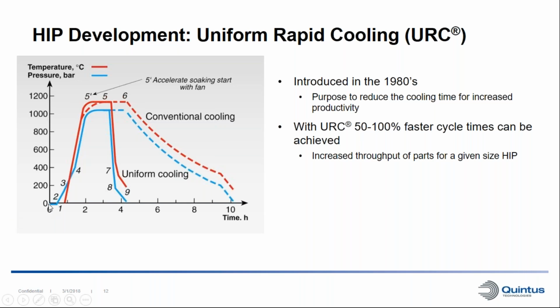So if we can see here on the left, a traditional HIP unit was, the cooling that you did was just to turn off the furnace and let the system cool down naturally. And the cooling time could be a significant part of the total cycle time. As we can see in this graph, we have many hours cooling where we're just waiting for the parts and the furnace to cool down so we can open the press and start a new cycle. So there's not really any value added in this part. With the uniform rapid cooling introduced, we could reduce this cooling time significantly so we can get increased throughput of parts for a given size HIP.